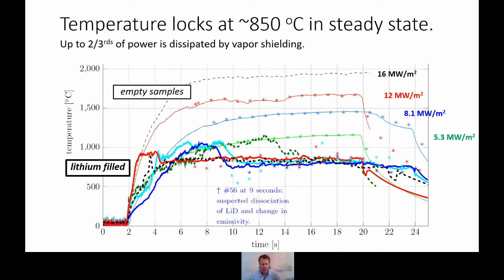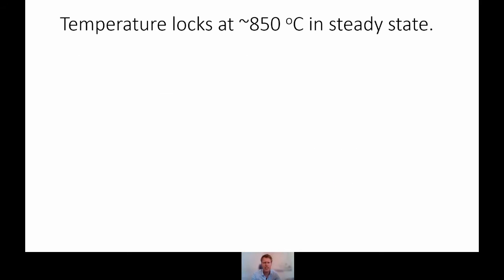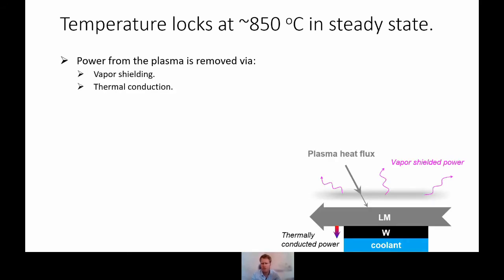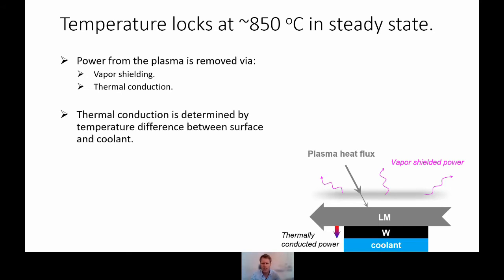So as I explained before, liquid metal evaporates. The liquid metal particles heat up, they ionize, they start radiating, they are transported elsewhere. In any case, heat is dissipated and not going to the target anymore. And in fact, we can say from this figure alone that probably up to 2/3 of the power is dissipated by vapor shielding for sure. And if you wonder how you can estimate that, think like this. So we know there is vapor shielding and, on the other hand, thermal conduction. Now, thermal conduction is determined by the temperature difference between the surface and coolant. And we know that the cooling water is at 20 degrees Celsius, at least in Magnum PSI, or whatever it is in another setup.